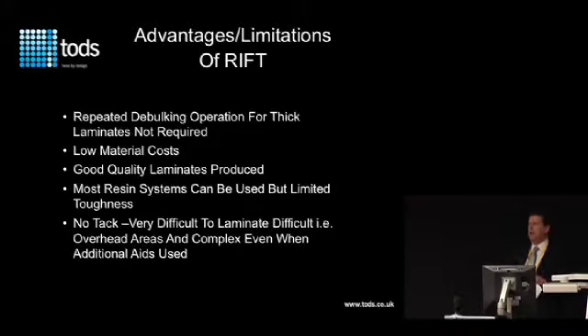Again, you don't need to do multiple debulks. The materials are very low cost. They're just fabric and resin. There's a limit to what toughness you can achieve, particularly with epoxy systems. As I said earlier, the toughening agents that are put into epoxies tend to increase the viscosity to a point where you can't readily infuse. The downside is there is no tack.